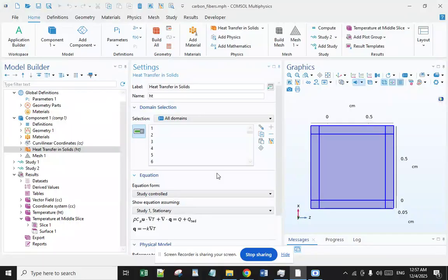Taking the value of the axial thermal conductivity of T300 carbon fibers as Kf, which is equal to 8.4 watt, and measured Vf equal to 0.35, the rule of mixtures yields a theoretically calculated KLL equal to 2.94 watt, which is very close to the experimental value, also taking into account the experimental errors.